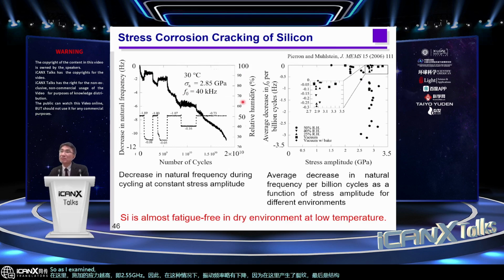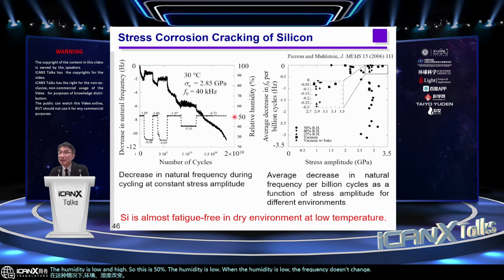In another example, the environment, the humidity, was changed, low and high. When the humidity is low, 50%, the frequency doesn't change. When the humidity is high, the frequency decreases because the crack is propagating, and finally maybe it breaks. Okay. So what we found is that silicon is almost fatigue-free in a dry environment at room temperature. So if we use silicon as a structural material, we don't need to care about fatigue problems.